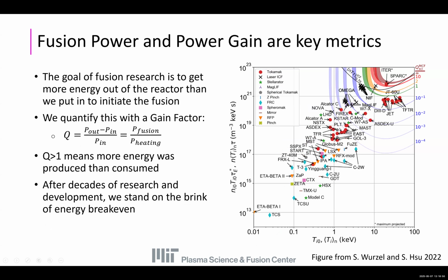So the goal of any sort of fusion reactor and research into fusion is to get more power out than we put into the plasma. And so the key metric that we use to quantify this is called the gain factor. We call it Q. It's defined to be equal to the ratio of the power out minus the power in, so the net power produced, divided by the power that you put into it. And so if you assume that you're in a steady state thermal equilibrium, this reduces to the fusion power divided by the heating power.